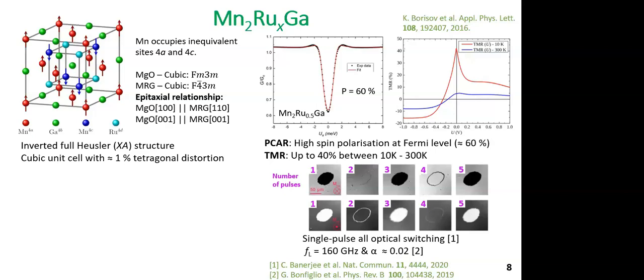So we have also observed thermally driven single pulse optical toggle switching, which is shown in the picture on the bottom right, where I'm showing you the number of pulses which were executed at the same spot. And we can see how the magnetization basically alternates from up to down.